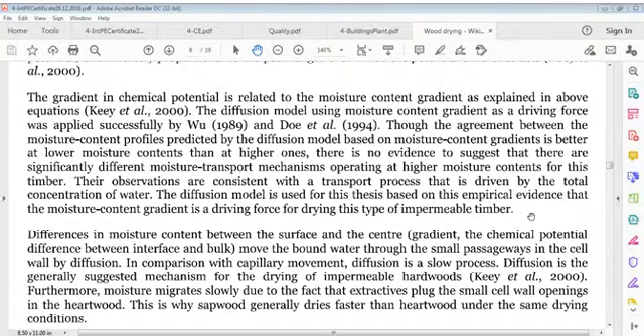Diffusion model using moisture content gradient as a driving force was applied. Though agreement between moisture content profiles predicted by diffusion model based on moisture content gradients is better at lower moisture content than at higher ones, there is no evidence to suggest that there are significantly different moisture transport mechanisms operating at higher moisture contents for this timber. Their observations are consistent with a transport process that is driven by total concentration of water. Diffusion model is used for this thesis based on this empirical evidence that moisture content gradient is a driving force for drying this type of impermeable timber.